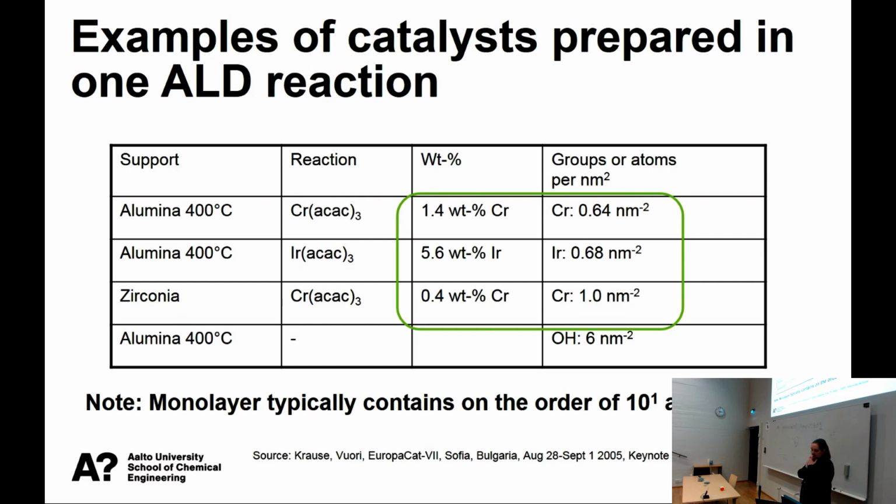And also what's interesting is that people think, of course, of the reaction mechanisms. Typically, hydroxyl groups, OH groups, are reactive sites. And if you read through the literature, you will find people assuming that there's a 1-to-1 correlation between the number of reactive sites and the amount of metals that you put in there.